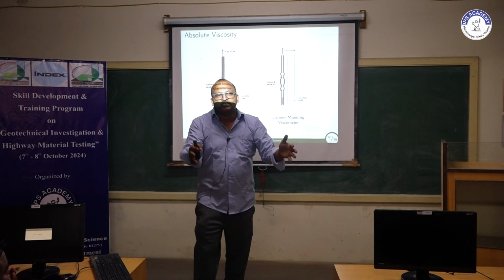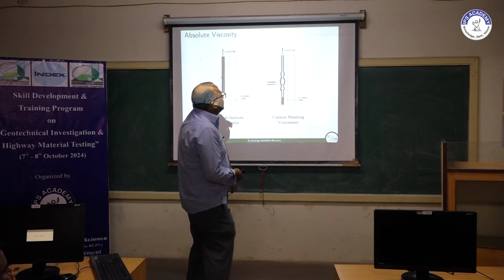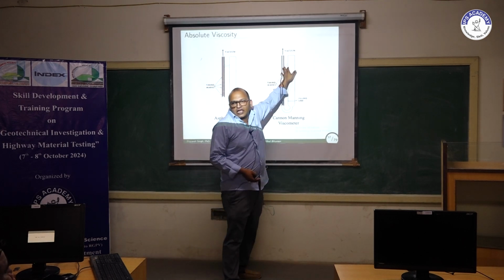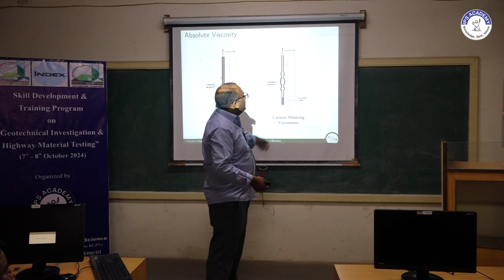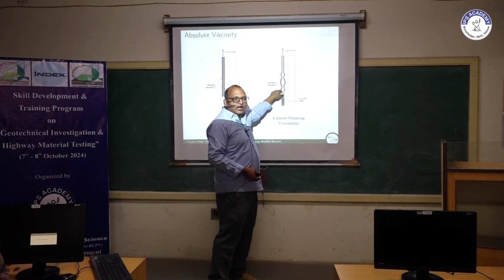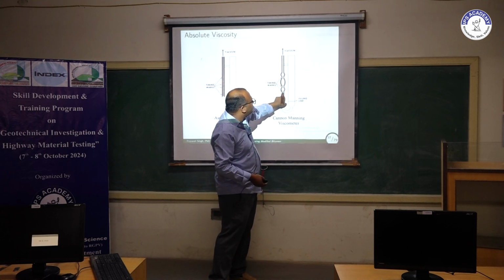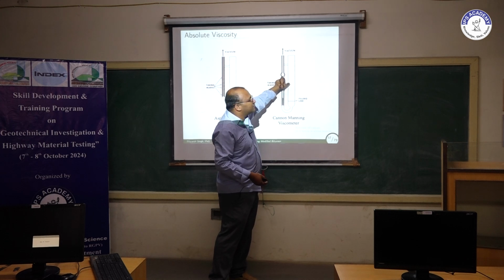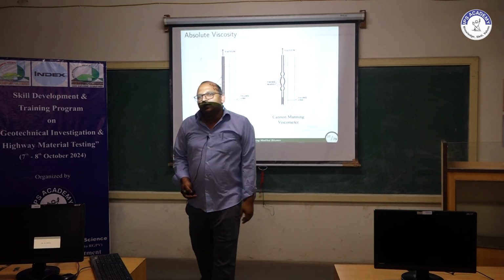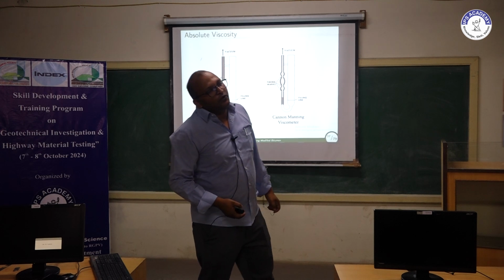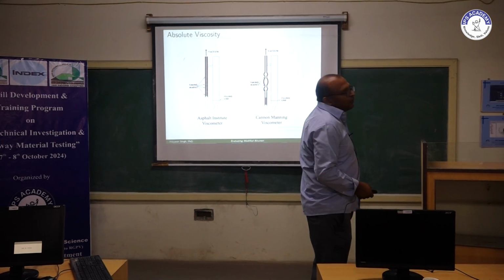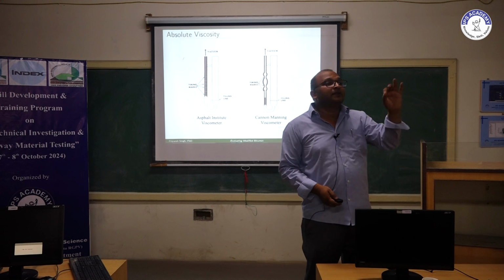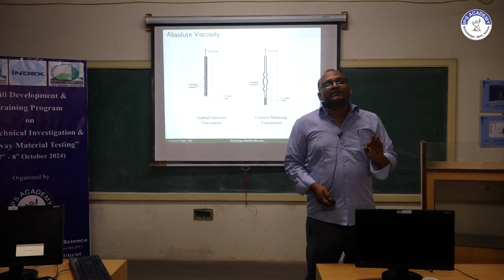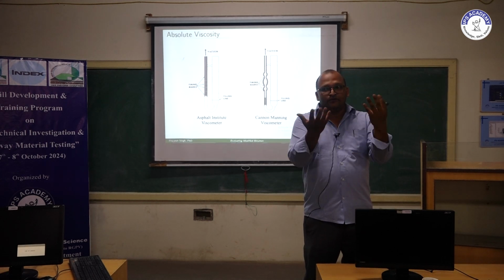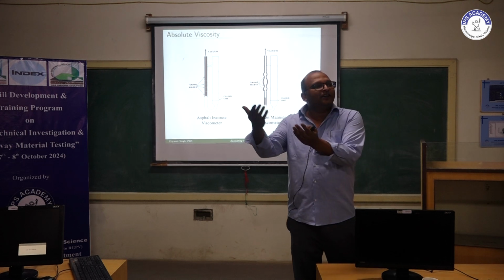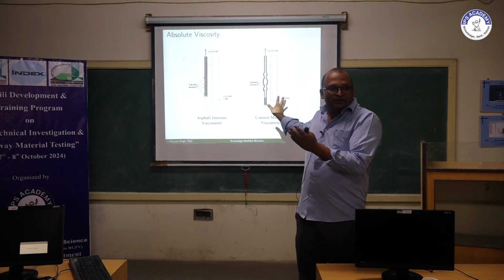We will keep it at the desired temperature, which is 60 degrees Celsius, and then we will apply a standard pressure, that is 300 mm of Hg, and because of the pressure the binder will flow, and we will record how much time it takes to cross from this mark to this mark and this mark to this mark. The average of these two multiplied by the constant of this tube will give you the absolute viscosity of your binder at 60 degrees Celsius. Now this is very important for viscosity grading, because what numbers you get, VG10, VG20 or VG30, that is because of this test.